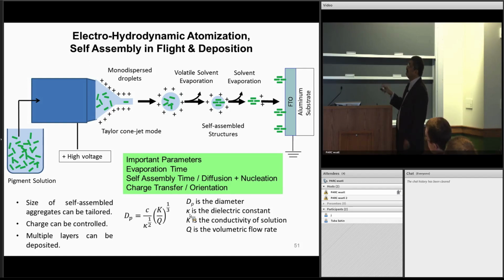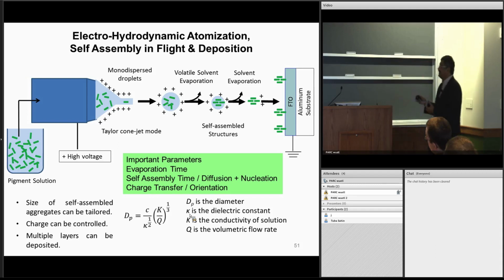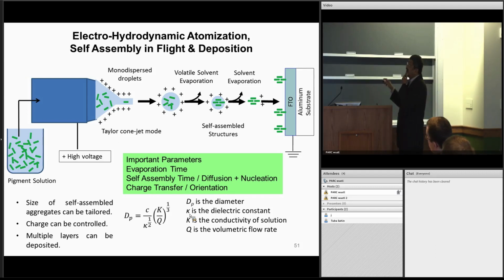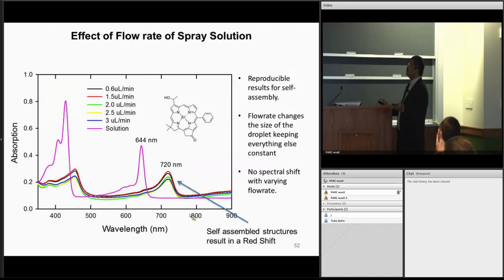This is where the diffusion maybe, or the nucleation, we are still trying to grapple with the kinetics here. And then eventually the charge transfer and the orientation, we want to even understand that. So this allows us to do that much more effectively in flight. Firstly, it's a single step, it allows us to do that and also deposit it.